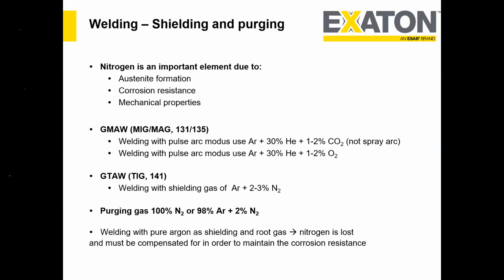Now, the most commonly used processes. It could actually be used with any process, but the most commonly used processes are TIG, MIG, and SMAW; submerged arc welding is also used, but in limited applications. I would say like 60 to 65% of applications are with the TIG process. There's another reason for TIG: in most cases, the duplex family grades have very high tensile and yield strength. So the designer has a chance to reduce the thickness when making the design calculation. Because of the high strength, the overall weight and the thickness can be reduced.